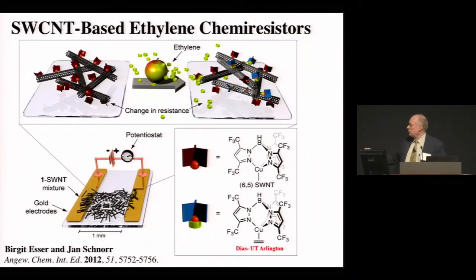We made use of some chemistry that was developed by Dias at UT Arlington, where he made these air-stable copper ethylene compounds. Okay, there are not a lot of air-stable metal complexes that bind ethylene, and this is kind of unique. So it binds the copper in a tetrahedral form, and it has these trifluoromethyl groups that basically withdraw electron density and make this nice and air-stable. So what we do is we initially make the copper that has a very weak ligand. We have toluene bound to it, and then we react it with the nanotubes, and it sticks to the nanotubes. Whoa, caught it. It sticks to those nanotubes like glue, okay?